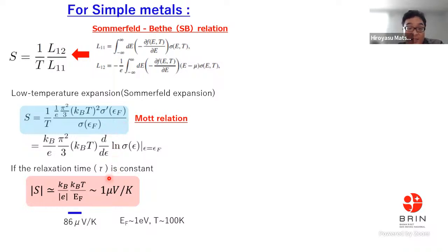And then by using the constant tau, we can get this equation. So the important point is the Seebeck is proportional to temperature, proportional to T. T is the temperature. And the amplitude is around 1 microvolt per Kelvin at 100 kelvins.